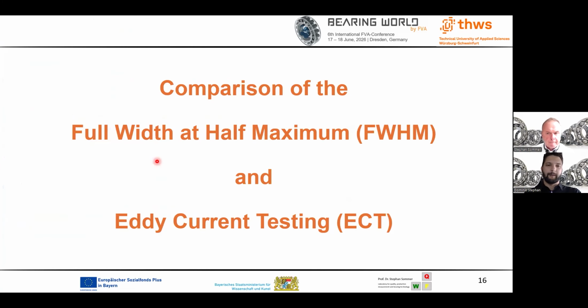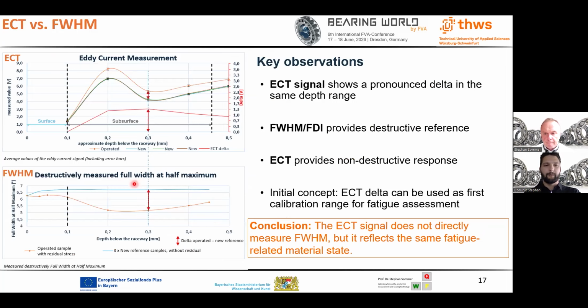The next comparison is between ECT and the full width at half maximum. For simplicity, I will refer to the full width at half maximum as FWHM. Here, we compare the ECT signal with the FWHM measurement. The FWHM values show a clear difference between the operated sample and the reference condition around 0.3 millimeters, in the same depth range where the ECT signal shows a pronounced delta.